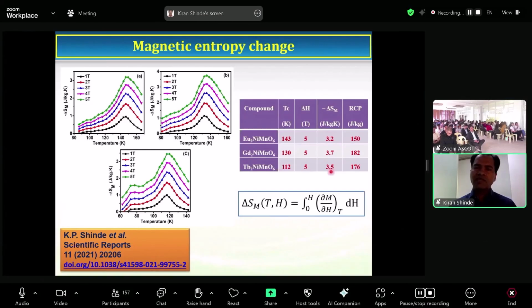But there is not a significant change in the delta SM value. And again, another parameter we have to determine is the relative cooling power, RCP, which is equal to minus delta SM into delta T FWHM. We have to use this formula to determine the relative cooling or cooling efficiency of the particular material. Here we can say there is a change in the cooling efficiency, but the important thing is we got a change in the Curie temperature, or we can tune the Curie temperature when we play with the A site.